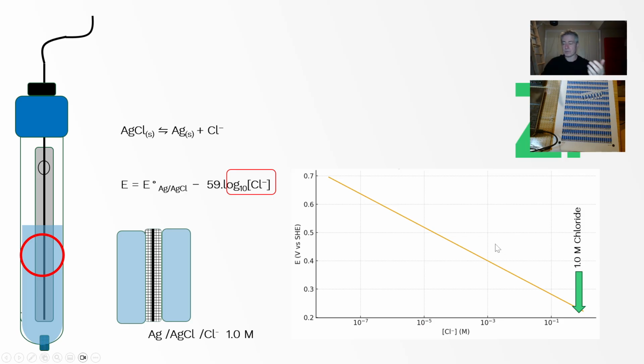But if, for some bizarre reason, you decided to actually dilute that chloride concentration by 10 times, then you would bring the potential there to a new potential. So the chloride concentration goes from 1 molar to 0.1 molar, and the reference potential would shift by 59 millivolts. Now, what does that mean when you're doing an experiment?